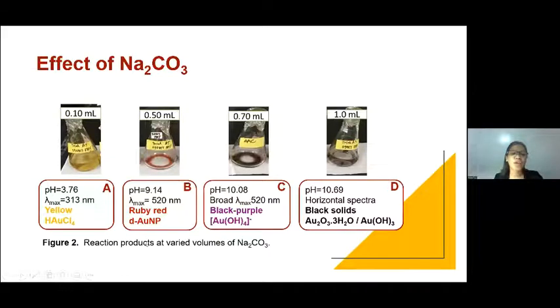Figure 2 shows the reaction products at varied volumes of sodium carbonate. Reaction with 0.1 ml sodium carbonate is a case with insufficient hydroxide ions for neutralization and reduction, and the resulting solution gives a yellow color with lambda max at 313 nanometers in trial A. Reaction mixture with 0.5 ml sodium carbonate is a case of sufficient hydroxide ions for both neutralization and reduction, and the result is a ruby red, stable gold nanoparticles with lambda max at 520 nanometers.